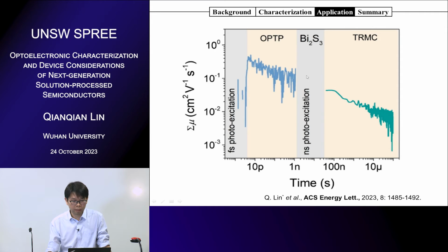from the time-resolved case, because normally terahertz spectroscopy can record the decay in the picosecond region. It's much faster. And we can also record the slower decays from TRMC. If you combine these two decays, you can get more information from these measurements. So we did it for bismuth sulfide recently.